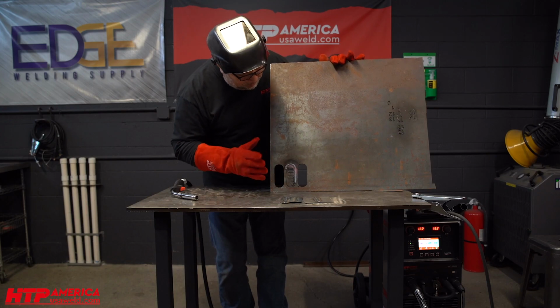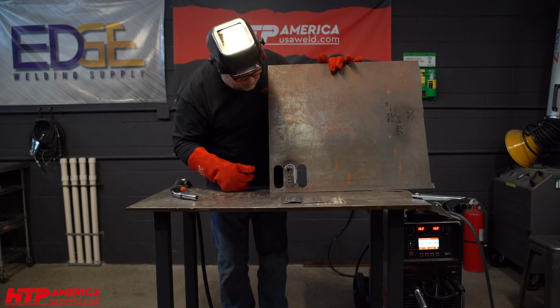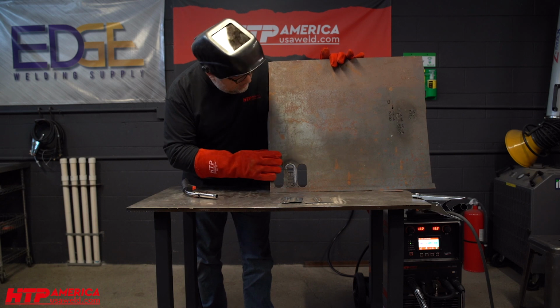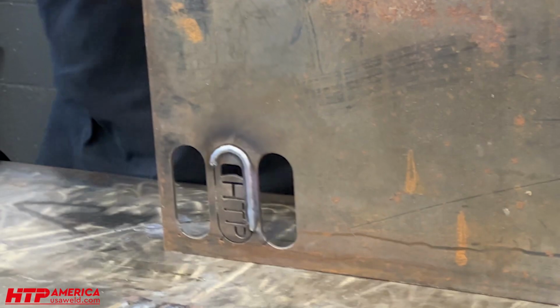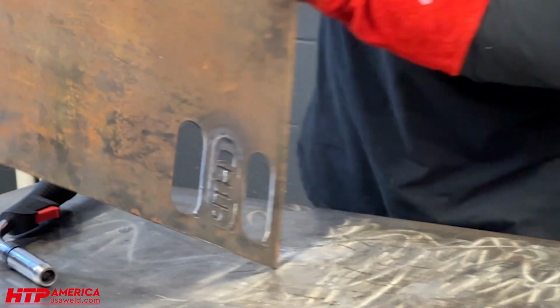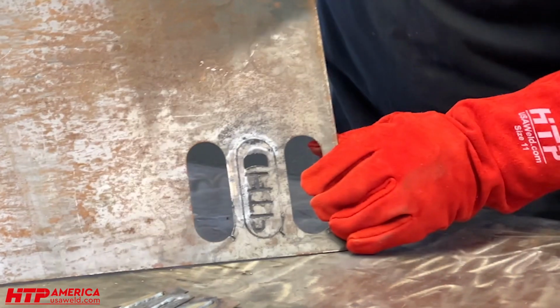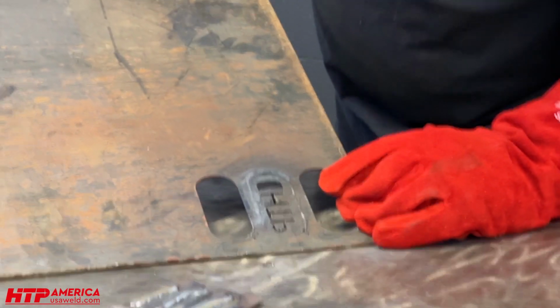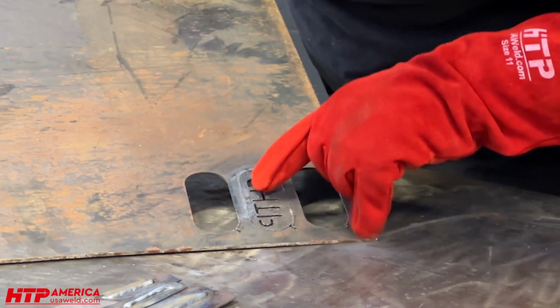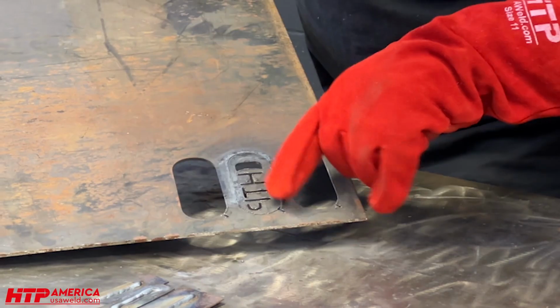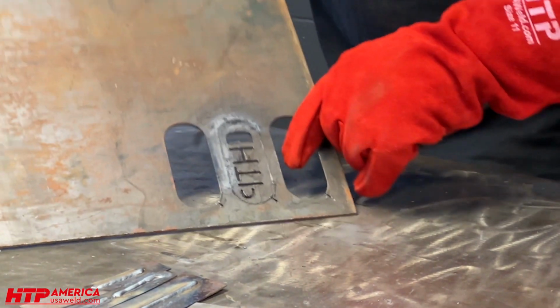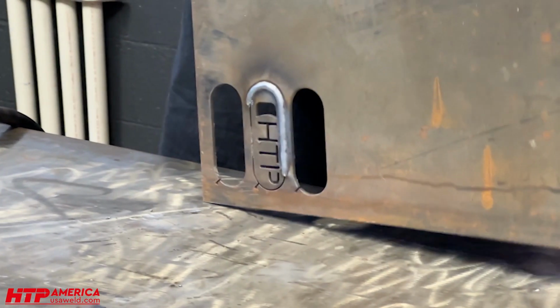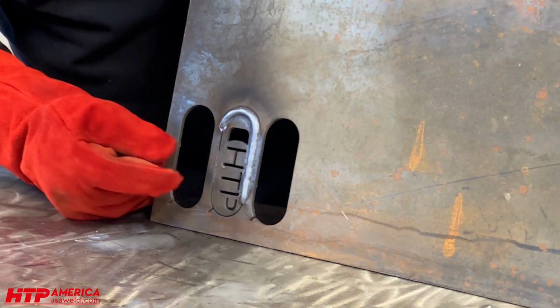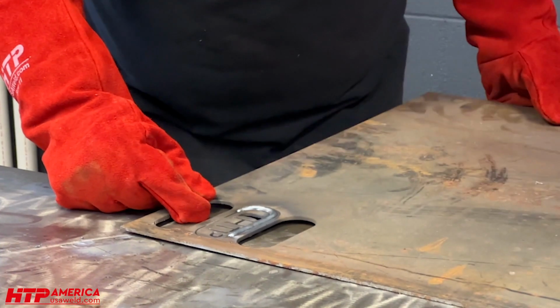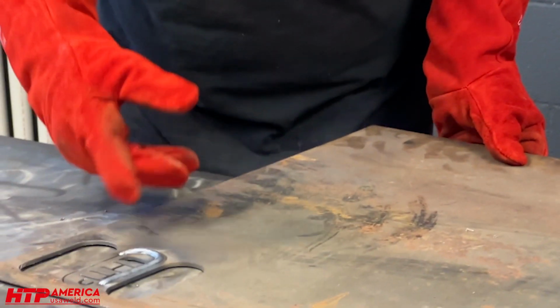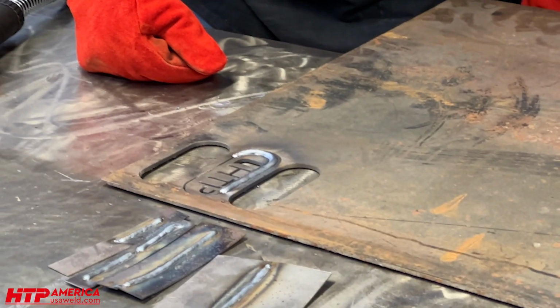Something you would find in your shop that has been laying on the water table for the plasma cutter a little bit too long. You have your mill scale on, you have a little bit of surface rust on it. Not crazy, but just enough to mess with things. And this was an unprepared plasma cut, and it basically filled most of the joint with that 60 thousandths curve that it left in there. So no, the machine is not intimidated by welding over the plasma cut, which, for what we started with, the results are absolutely amazing in my mind.